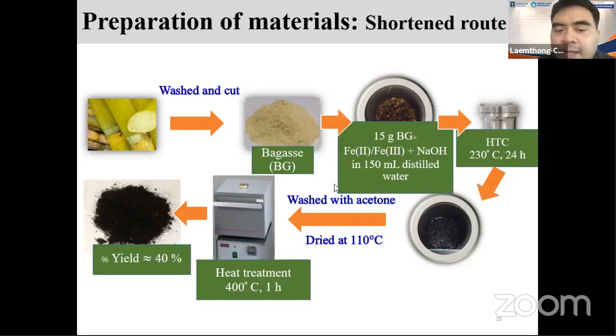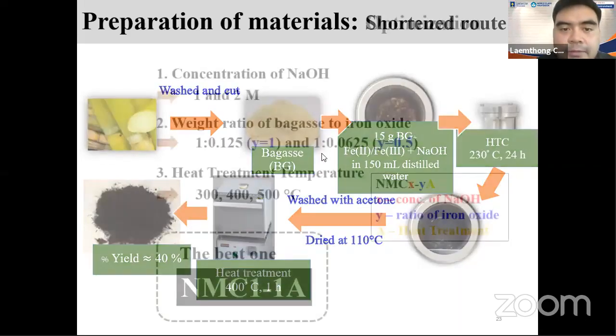And compared to the pyrolysis technique, they have to use a lot of chemicals and they have the washing process. We actually have to wash out a lot of toxic chemicals like sodium hydroxide, potassium hydroxide, or zinc chloride out of their system. And of course, they have a lower yield, but we have the higher yield. We have around 40% compared to the raw bagasse material.